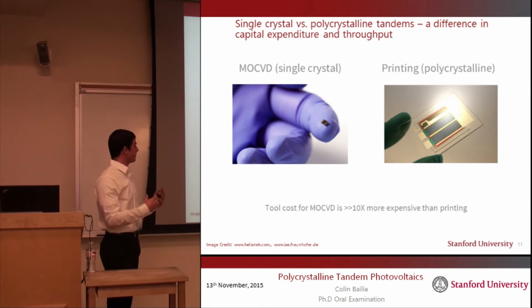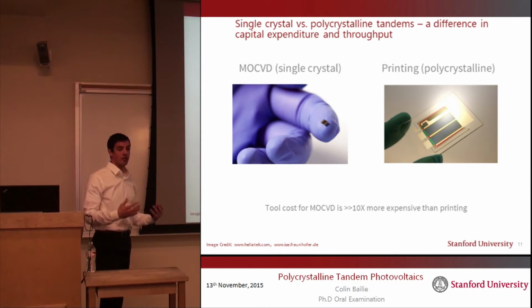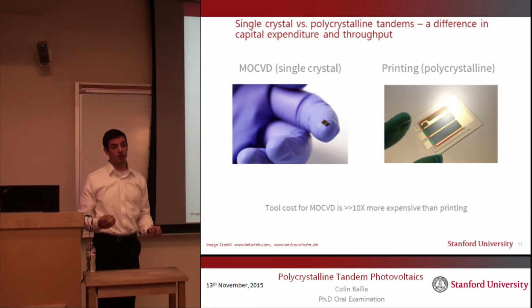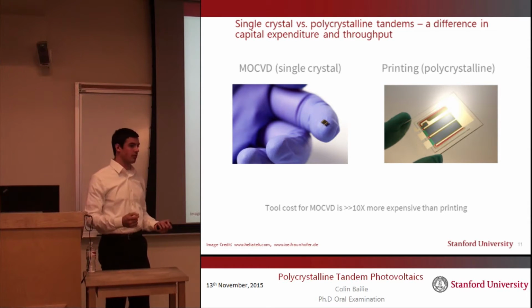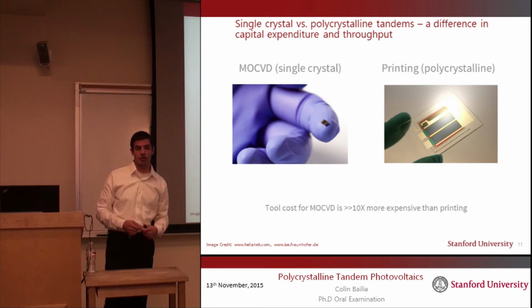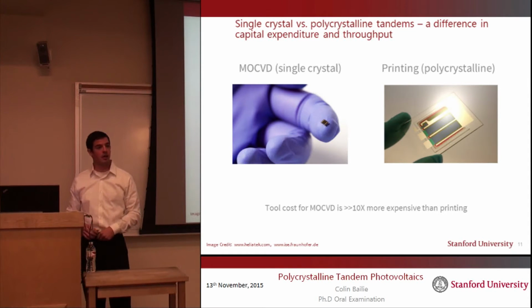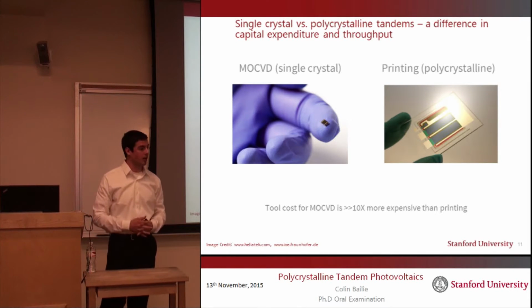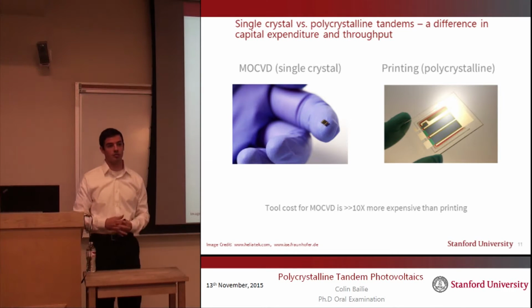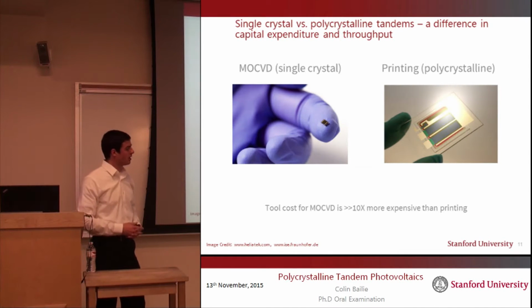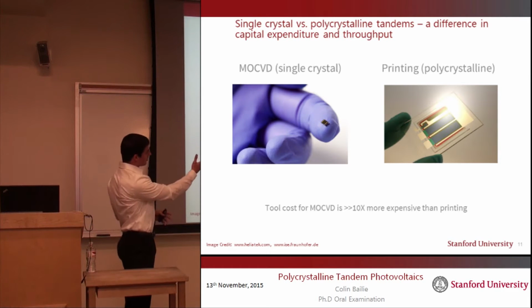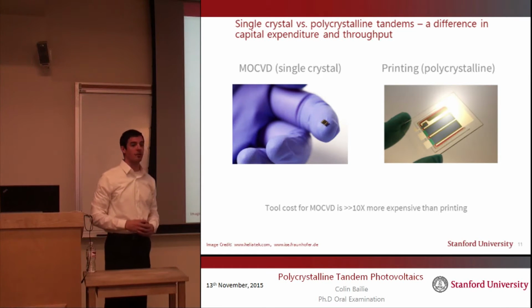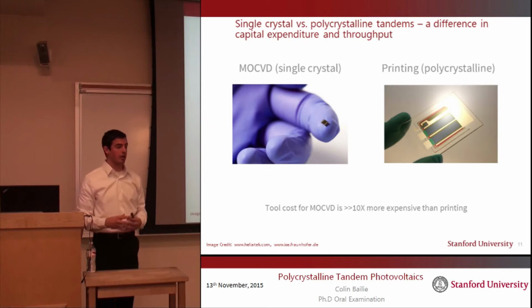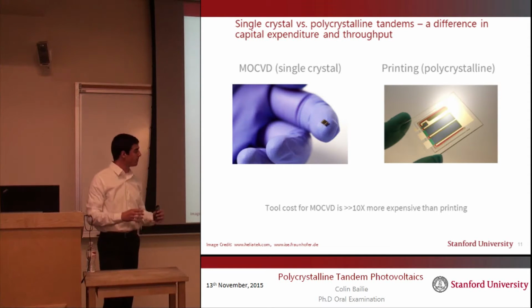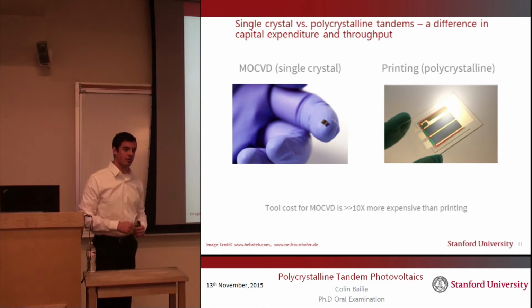You have to grow it as a single crystal, which means you have to use specialized tooling, and you have to grow it at a low throughput. So what we'd like to do is to be able to not worry about having to grow our solar cell as a single crystal, and instead make it polycrystalline, which opens up the options for things like printing, which uses low-cost tooling and is compatible with high throughput, and those exist too. So this image on the right is of an organic tandem, and this organic tandem has the cost structure that we'd like, but it's probably only about 10% efficient.